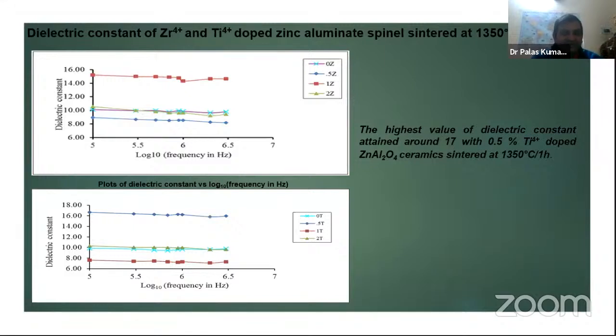And just one point to add: a dielectric constant ranging from 10 to 20 and a loss factor of 0.01 to 0.02 are very suitable for microwave applications, especially the lower end. This is already commercially produced, but only using pure zinc aluminate, not doped with titanium and zirconia. Might be some different kind of dopant.